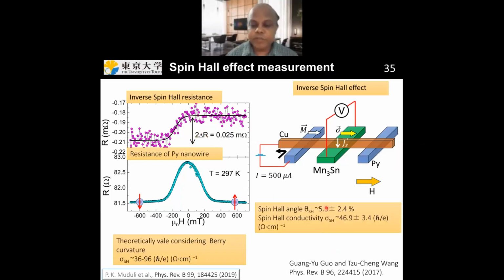From this experiment, I found the spin Hall angle of Mn3Sn is 5%, which is very close to the spin Hall angle determined for platinum using the same experimental method. The spin Hall conductivity was found to be 46 ohm^-1 cm^-1, which is very close to the theoretically predicted value calculated using Berry curvature in the band structure. So this confirms that although we had a polycrystalline sample, not very good quality Mn3Sn, you can still get a very large spin Hall conductivity, comparable to theoretical predictions. So the spin Hall conductivity in this material is mostly intrinsic dominated.